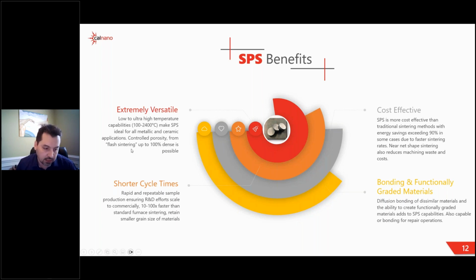And that's actually a growing need for things like heat pipes and heat sinks and catalysts and filters, where we can get very strong interparticle bonding, but without collapsing the pores inside by having a very low or minimum pressure. And we can get a very strong mechanical bond between those particles, allowing the final product to be an engineering material without having those porosities, as I mentioned, keeping a very high surface area and tortuous gas paths through the material.